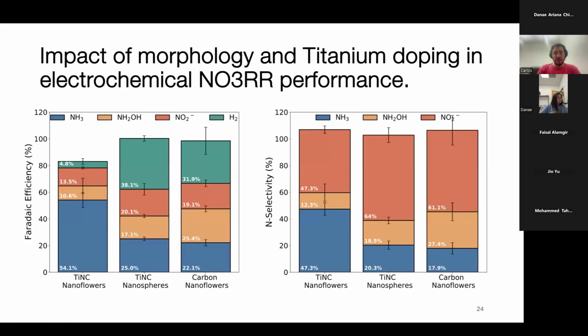And we compare the performance of these different nanoparticles, and you can see that the selectivity of the titanium doped carbon nanoflowers improves by large amounts. It doubles compared to the nanospheres and the carbon nanoflowers, as well as the nitrogen balance almost nearly more than doubles. And you can see that both the carbon nanoflowers and the titanium doped carbon spheres lead to a lot more hydrogen production compared to ammonia, and also they produce a lot more nitrites and hydroxylamine. So we have kind of optimized this catalyst to be more selective towards ammonia.